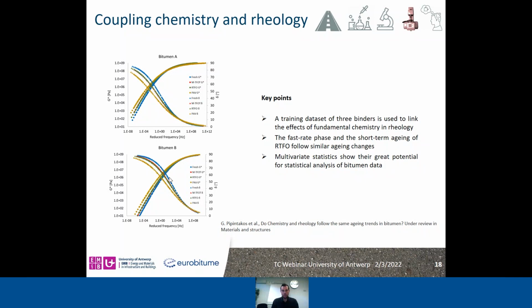But of course, this is just a visual observation, and for that reason, statistical analysis was performed on the master curves, and more specifically on the parameters of them. The key points of this study are that we propose a training data set of 3 binders that vary a lot between them in order to link effects of aging in chemistry and rheology, and also to show that there is a great potential for statistics and multivariate statistics for bitumen applications, especially if the library of this dataset can be expanded to extracted binders and also modified ones, since this PhD work focused only on conventional binders.